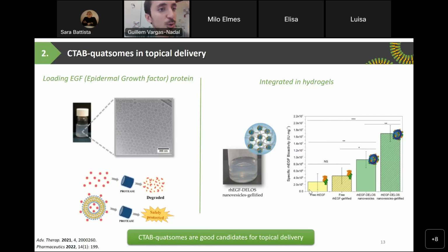They have been developed in order to load EGF, which is an epidermal growth factor, which is a protein. And here you can see a cryo-TEM image, and they also protect the EGF from being degraded by a protease. So in this case, the CTAB quatsomes protect the EGFs, and these quatsomes with EGFs have been integrated in hydrogels. You can also see in this graph that the bioactivity of the EGF is enhanced even when the quatsomes are jellified in the hydrogels. So the CTAB quatsomes are good candidates for topical delivery in order to deliver this EGF protein in the skin.